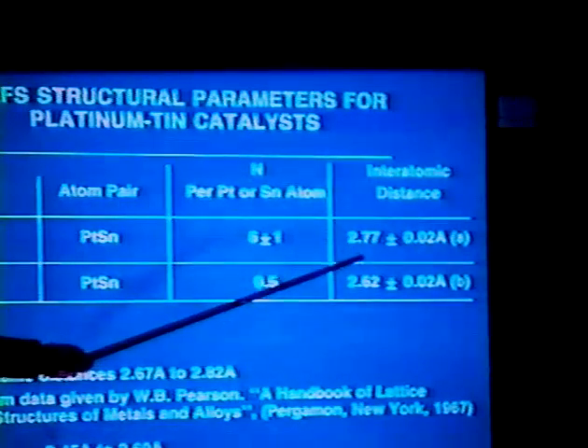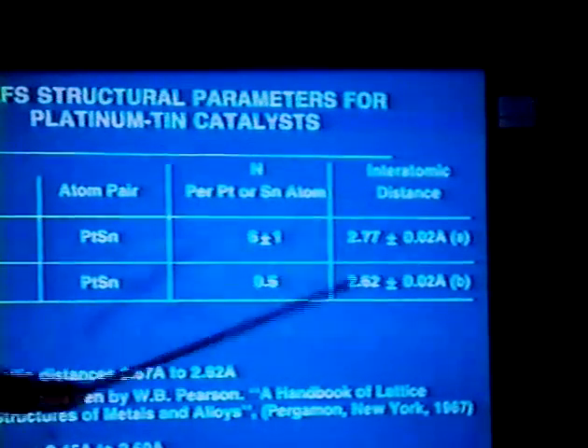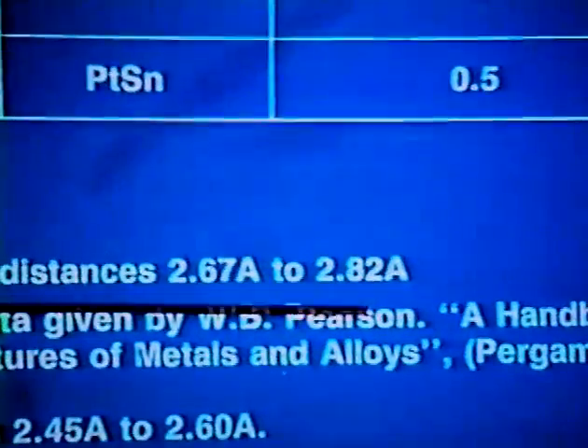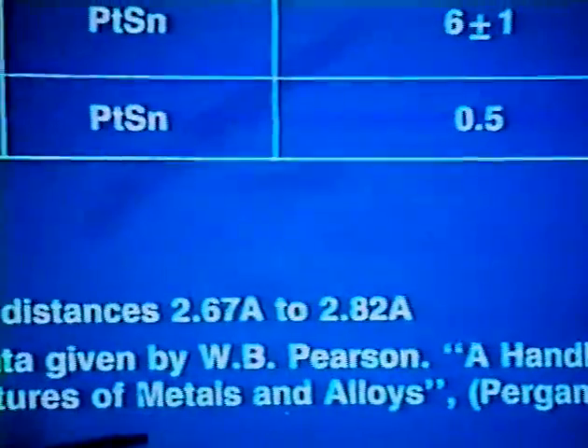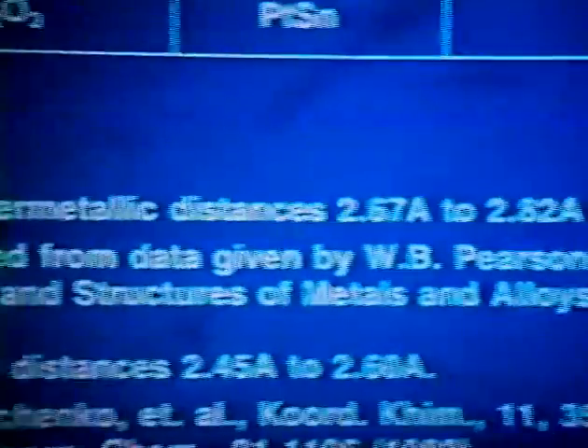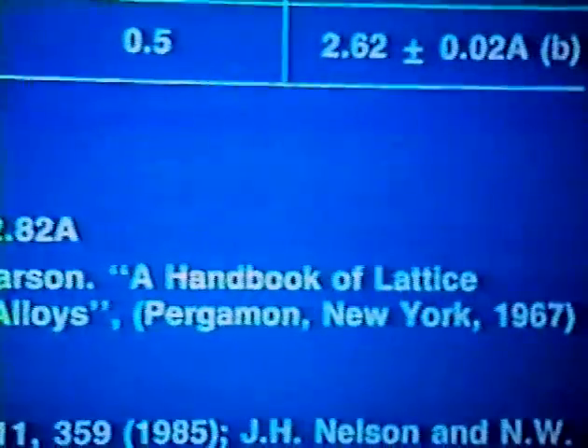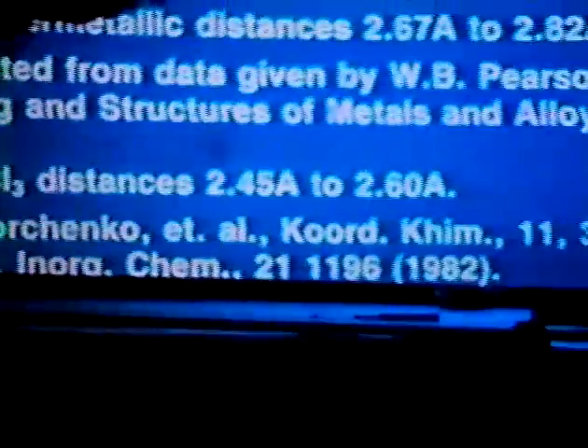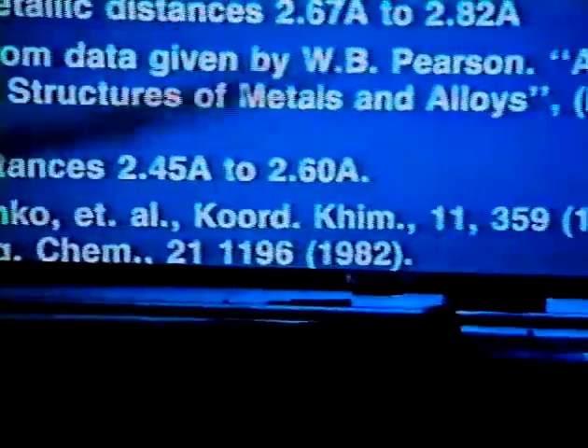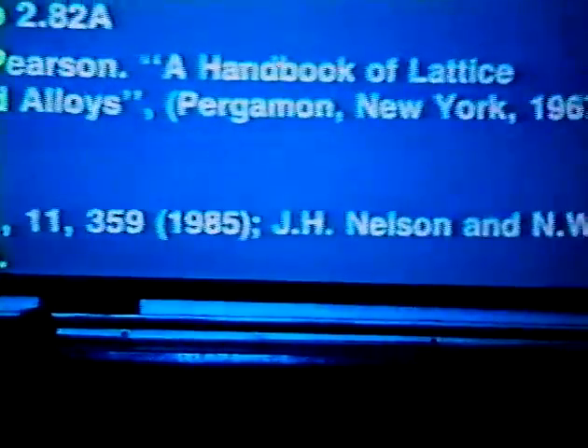The interatomic distances are informative, the platinum tin interatomic distance. On the silica-supported system, it's about 2.77 angstroms. Well, in the various intermetallic compounds formed by platinum and tin, the platinum tin distances are in the range of about 2.7 to 2.8 angstroms, which includes this distance. And in fact, platinum and tin on silica form intermetallics. The tin gets reduced to tin metal, and it reacts quite exothermically with platinum, and you get ordered solid solutions of platinum and tin. That's why we see this metal-rich environment for both, and that's why we see this particular distance for platinum and tin.